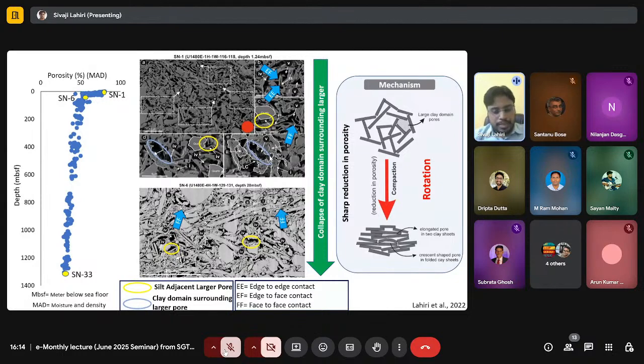Now, based on this observation, we can conclude collapse of clay domain surrounding larger pores caused rapid or sharp reduction in porosity at the shallow depth.